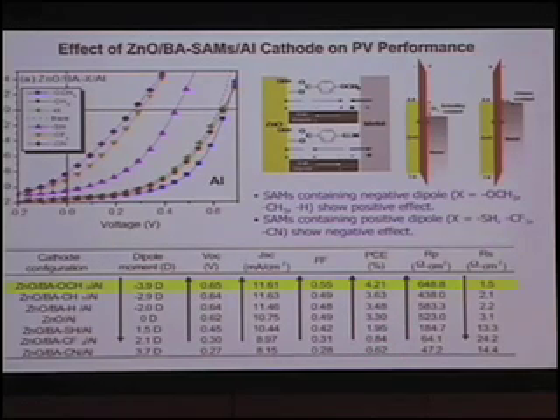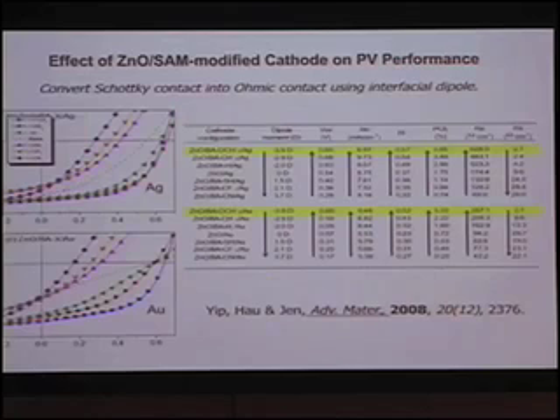So if you look at this, this is the one without the dipole. Because aluminum has a work function of about 4.2 electron volts, which is very close to zinc oxide, you don't really get that much net benefit. However, when you take a higher work function metal, like silver and gold, originally, if I don't have this SAM, you have a very poor performance, here, this dotted line. But when you introduce this layer of SAM, you have significantly improved the device performance.